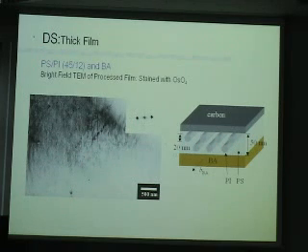Another thing we considered is the film thickness effect. So you can just imagine, in this case the cylinders tend to lie down. Cylinders have more entropy lying down like this. But when we decrease the film thickness, say below 20 nanometers, we have to consider the boundary condition.